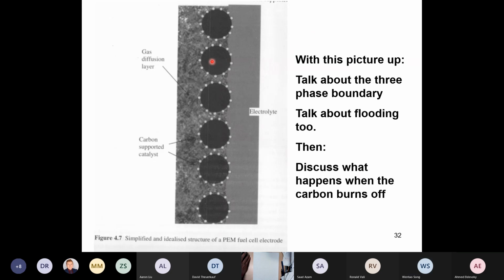You know, but still, at 80 or 90, the saturated vapor pressure of water is quite high. So you can have a lot of water content in the air before you condense liquid water. But still, it's possible to condense liquid water if you can't get it away fast enough from the particles.